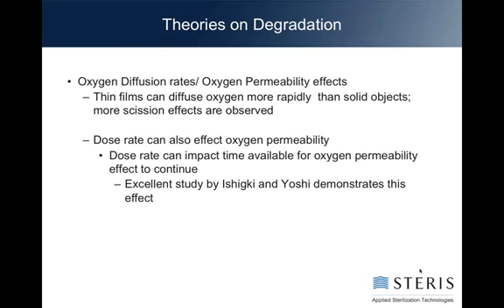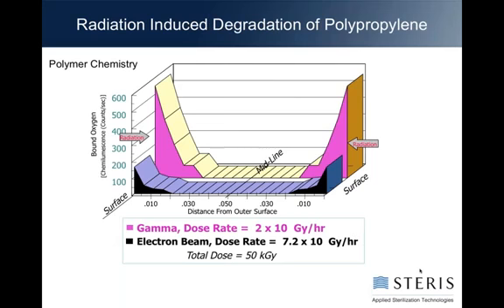Another thing we've learned is that dose rate can affect oxygen permeability. So if you think about the longer it takes to deliver your dose, that's a longer period of time when the conditions for a change to occur are there. You have oxygen present and you have an ionizing field. So dose rate can impact the available oxygen in the product. And as an article at the end, the reference is the particular authors that has a whole bunch of data where they've demonstrated that permeability.